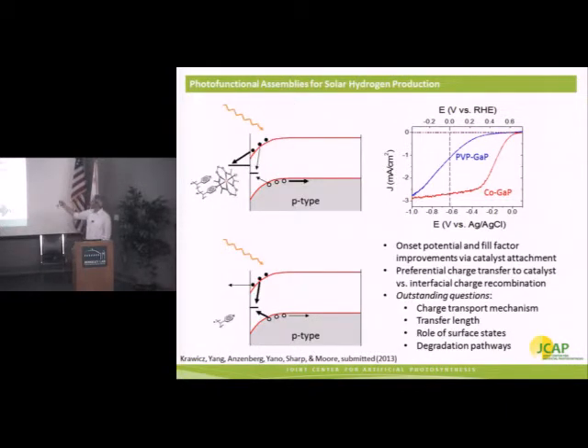To understand this curve a little bit better, the difference between these two, we can look again at these band structures, or these band diagrams. For the case of the polyvinyl pyridine, we have no catalyst on the surface, but we do have interfacial defect states that can lead to charge recombination. So here again we have the electrons being accelerated to the surface by the built-in electric field, but there are surface defects that can trap those electrons and lead to recombination with holes. That means that we've absorbed a photon, we've created free charge, and then we've recombined it without doing any chemistry. That's a direct efficiency loss.